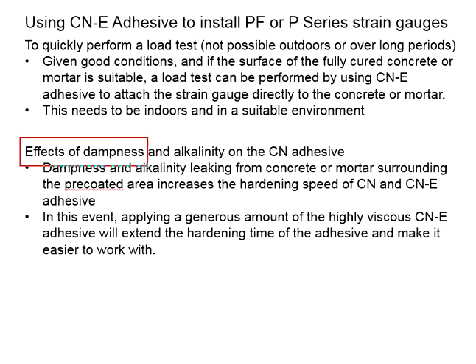Next, let us talk about the effects of dampness and alkalinity on the CN adhesive. First, what is dampness? It is referring to the state of the surface where you install the strain gauge, which is slightly wet. How about the alkalinity? This one is due to the chemical compound from the reactions of the concrete or mortar during the hardening process. Now, in the existence of the dampness and alkalinity surrounding the pre-coated area, this may increase the hardening speed of CN or CNE adhesive. If it hardens very fast, you might have difficulty installing the strain gauge in the precise locations, as you have to work faster than usual before the adhesive hardens.